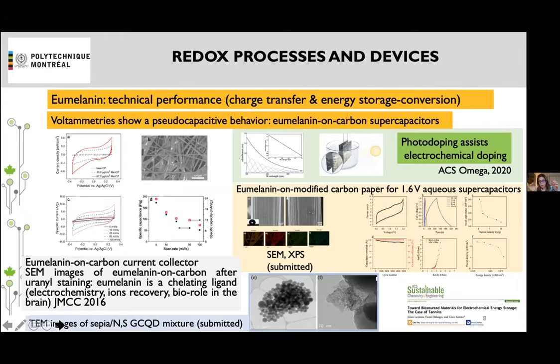supercapacitors whose working principle is really the redox activity of the biopigment. So we deposit the biopigment on carbon and we have the capacitive component, purely electrostatic, due to the presence of the carbon current collector, but we add on the redox activity of the eumelanin. And so we enhance, if you want, the charge storage property of the device. Absolutely state of the art in terms of performance.